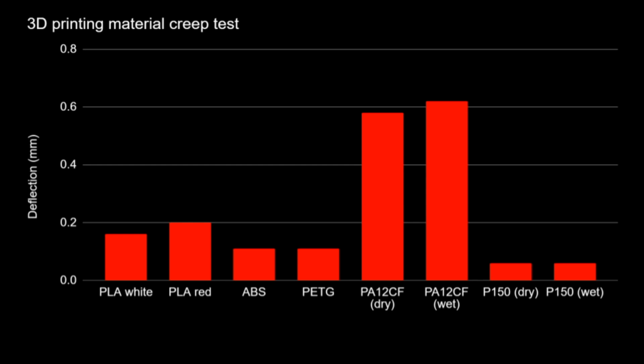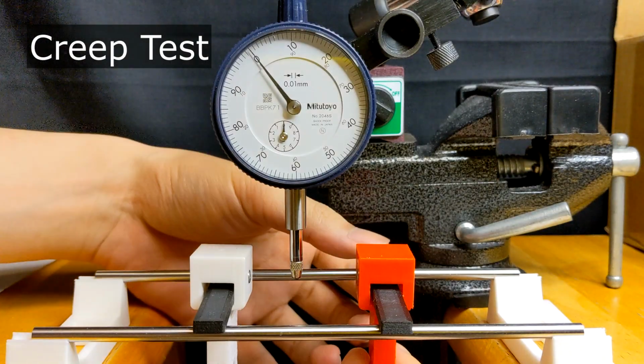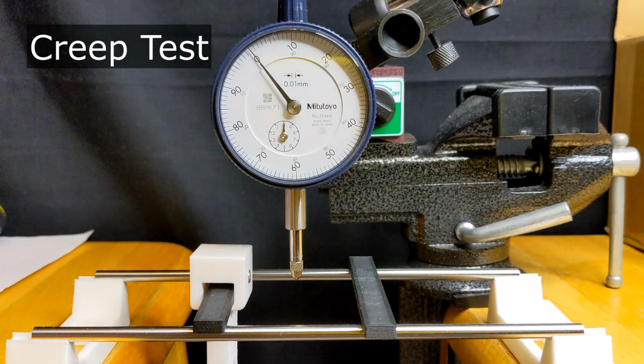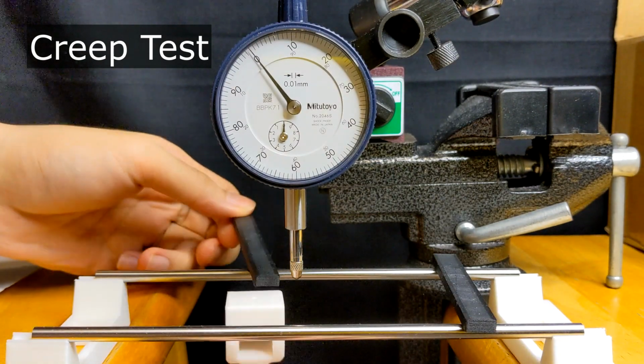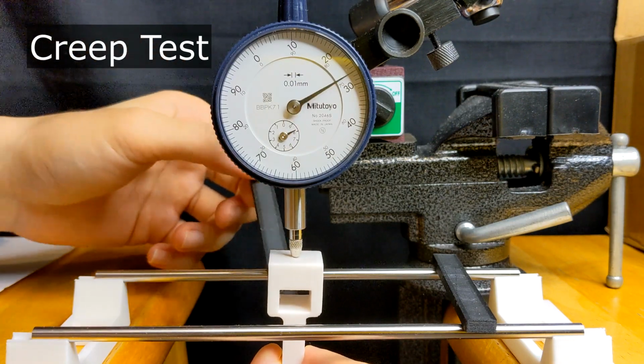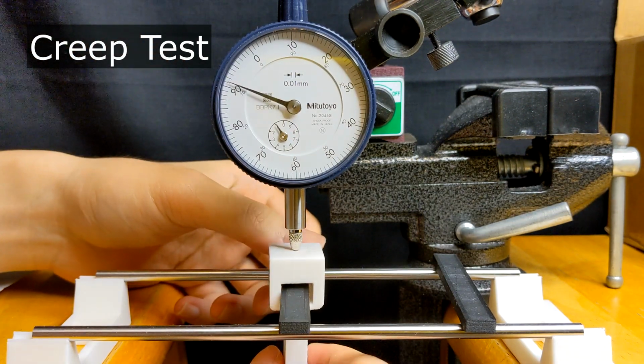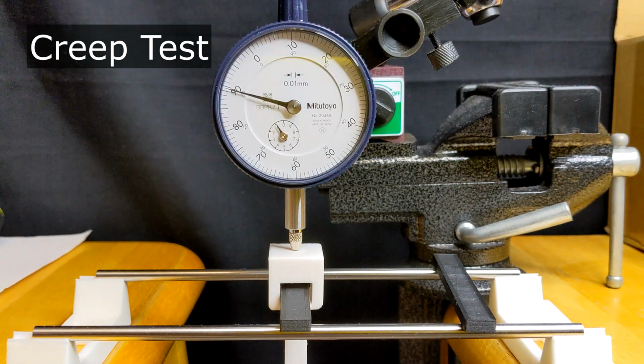As the diagram shows, the dry samples share the same results as the wet ones. It means moisture is not a critical factor in creep. The deflections are incredibly lower than other materials, which again makes it suitable for frame structures. As a structural material, P150 has a role to play. It provides not only stiffness but also low creep performance, making this lightweight material a choice for frames and structural parts. Here are the tests for the Igumid P150.